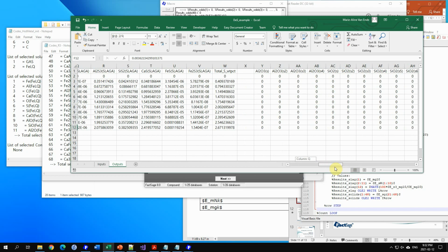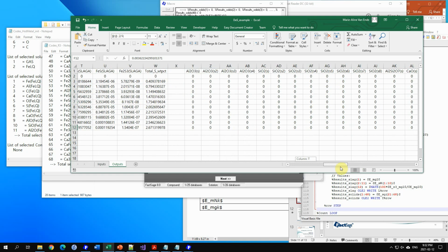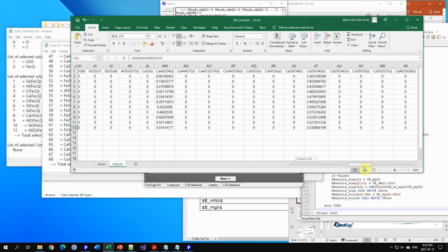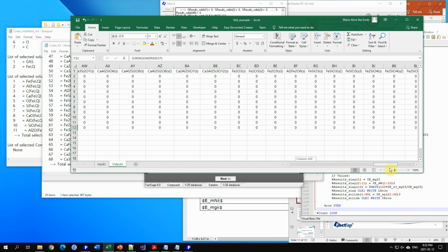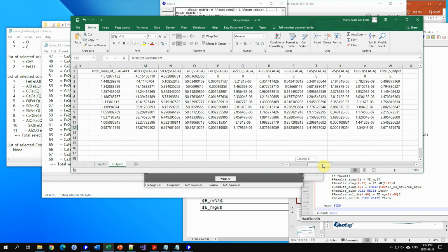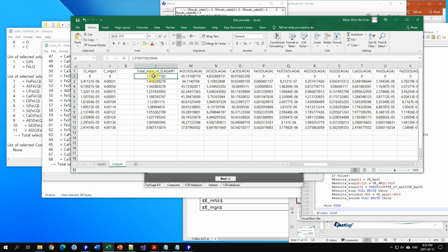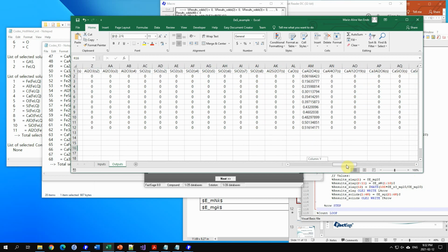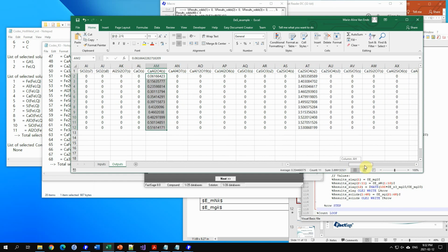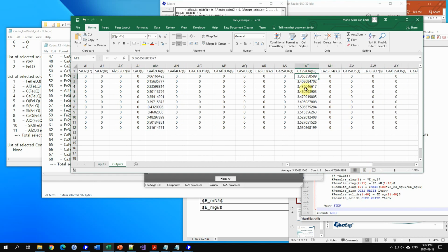And then we have some solids. You can see basically calcium aluminate, CaAl2O4, and C2S, Ca2SiO4 are created, and we don't have any other solids, 2 solids form. And then we see also that as the process is going on, the mass of liquid slag decreases, and the mass of calcium aluminate increases gradually, as well as that of C2S.